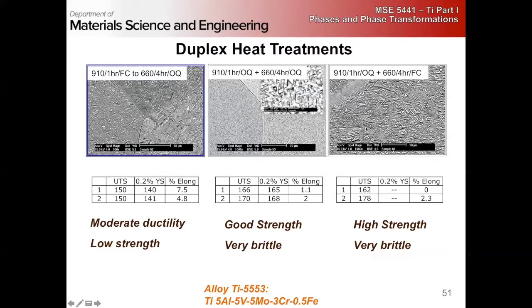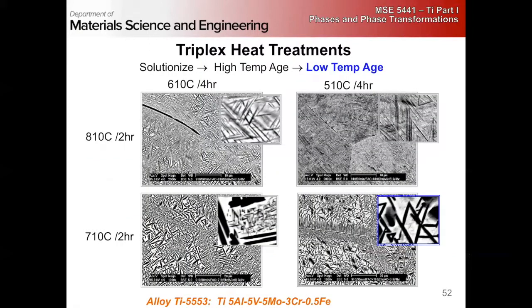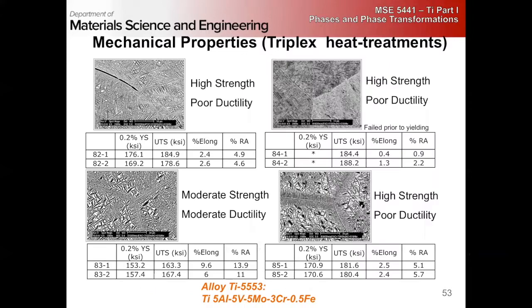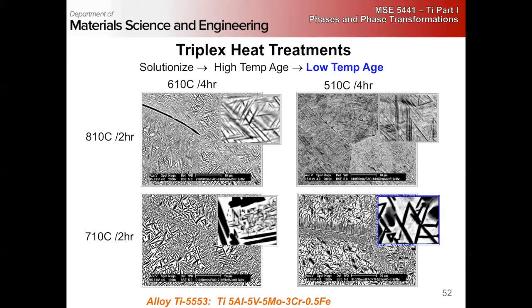This has the highest strength, but the ductility in these is only 2% elongation or so to failure. And so this condition where you have good strengths but low ductility led to the invention of these triplex heat treatments, which are kind of the norm now. And you'll notice they're not super successful in the fact that they still generally have pretty poor ductility.